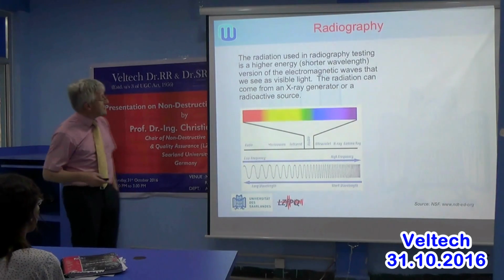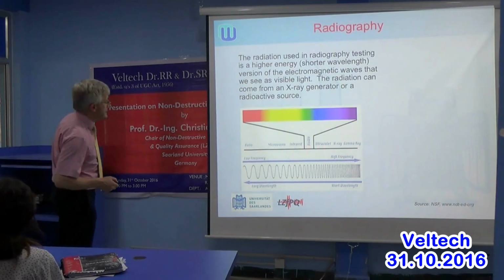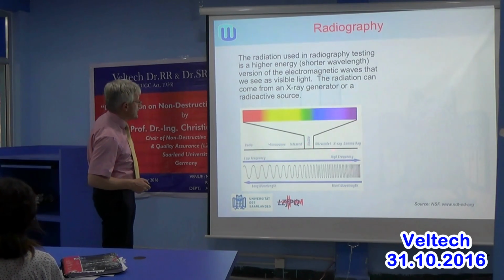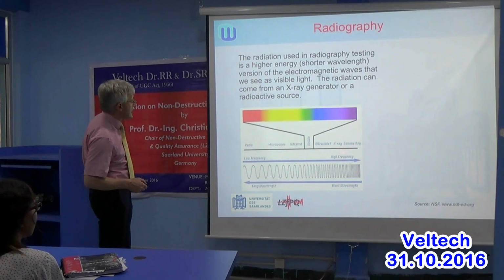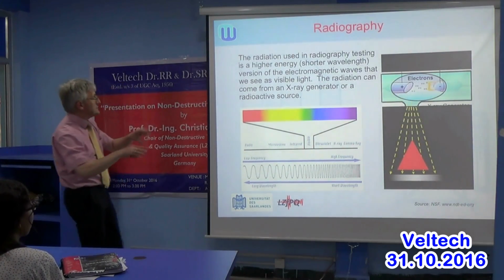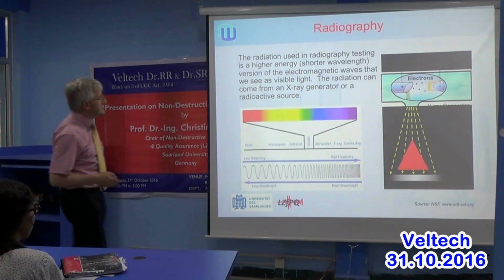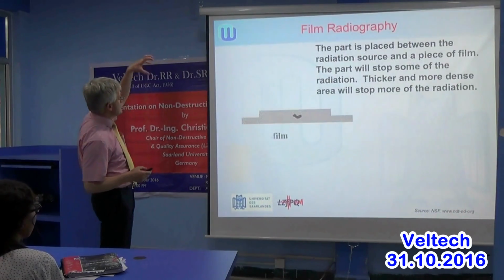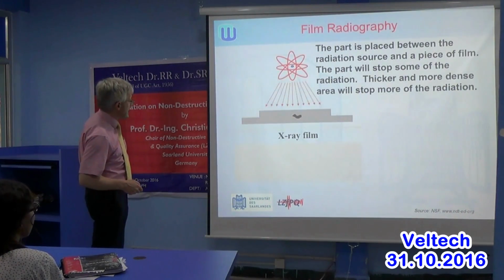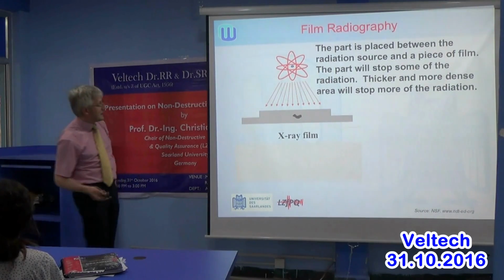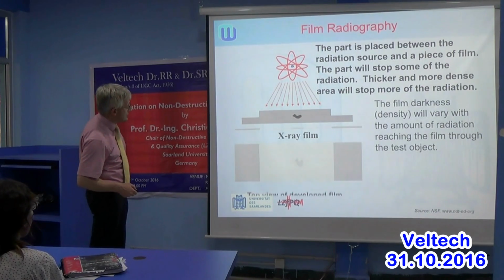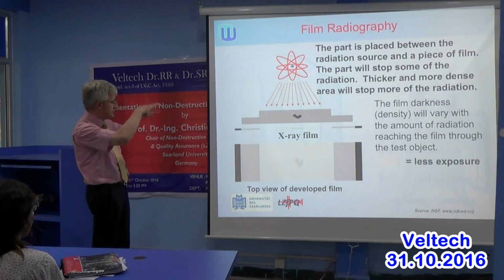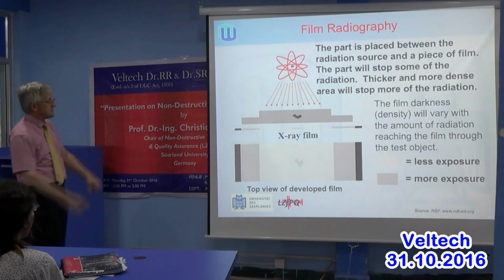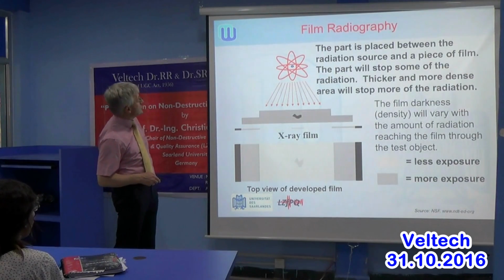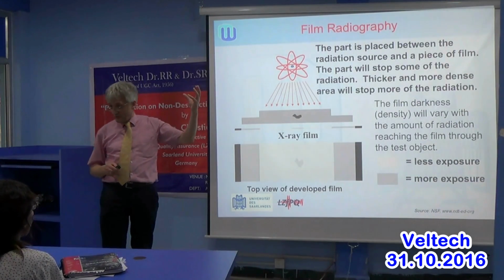Right, then radiography is something very popular in medicine. This is the visible range, and you go to a high frequency electromagnetic wave, so in the X-ray and gamma ray range, depending on the source, we can either generate that artificially or naturally. We send a radiographic signal through the component, and we take an image, either digitally or on a film, and we will see on the image a resolution depending on flaws inside. We can do this at different levels and from different directions, and we can get a full 3D image of what we're looking into, at very, very high resolution. But of course, the effort is not a small one.